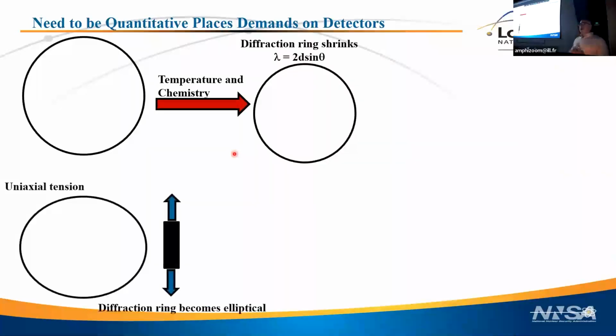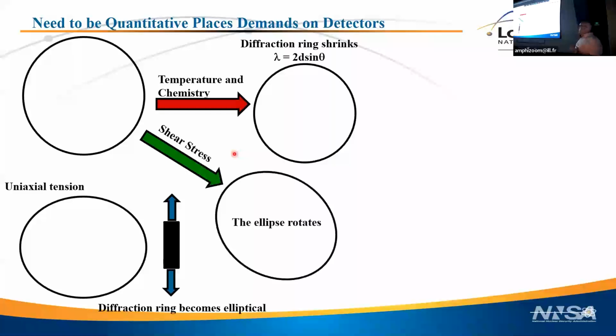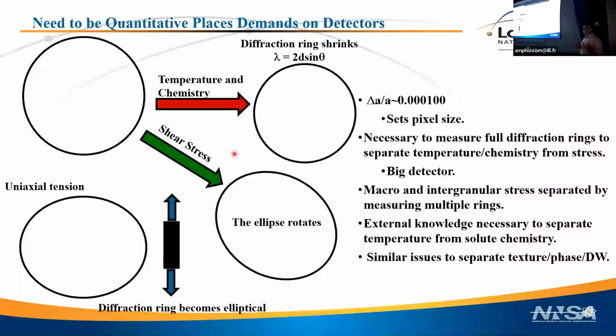If you put a stress on it, you change the shape of the Debye-Scherrer cone. You turn it into an ellipse. So if I pull on it, the direction that I pull on it actually gets smaller 2 theta, because as d-spacing gets big, of course, it's an inverse relationship. So theoretically, I can separate those two effects because one changes the radius and one changes the shape. And finally, if my stress isn't uniaxial, if I have a shear, then that ellipse actually rotates. Okay, so I can separate those three effects because if I measure the full ring, then I can separate what's temperature from stress and shear in this case.